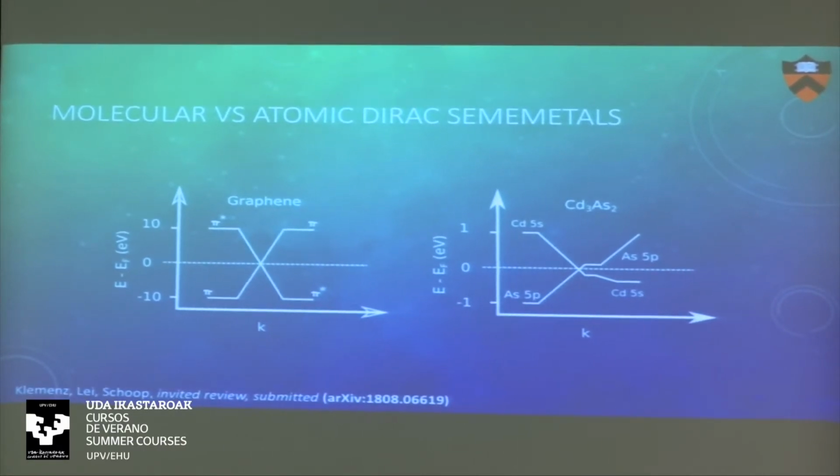So it's just one atom that's causing the band inversion. I call these atomic Dirac semimetals and these molecular ones. What I want to point out is that these are way superior, because this is just a rough sketch, but in graphene, the band inversion energy, the region these linear bands span and invert, is huge on a huge scale. In cadmium arsenide and sodium-three bismuth, the other ones, it is tiny. That's also a problem for a lot of TIs. So this kind of molecular type of band inversion is what you want to get the good materials.